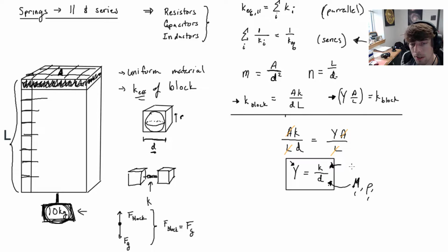If my recollection serves me correctly, it's not very big. It's something like, I think for copper, somewhere around 10 newtons per meter, which is a fairly weak spring. You don't think of copper being that weak, but the issue is that you have so many copper atoms in a cross-sectional area that even though an individual spring might be really weak, the summation of them is huge, just absolutely huge.